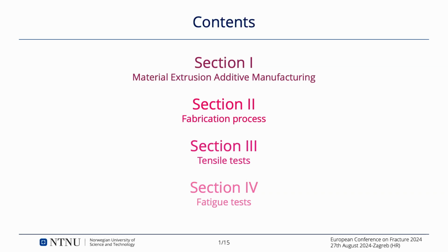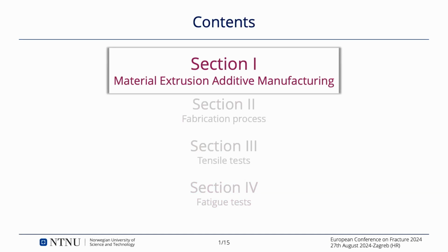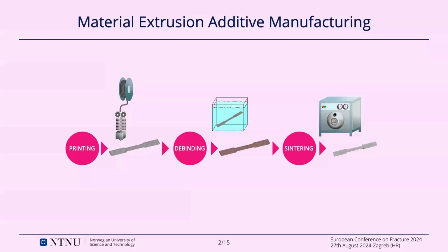And then I will present the results for two batches of results, one for tensile tests and one for axial fatigue tests. So we can start with material extrusion. It is actually a three-phase process, and the additive manufacturing is only the first phase, the printing phase. Then we have the debinding and sintering.